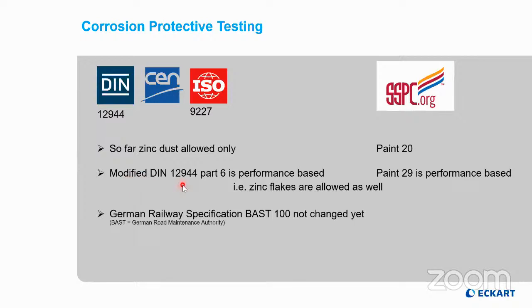This norm has now been changed into also a performance-based norm, meaning zinc is still specified in the norm, but not by 85% loading. It needs to be loaded into the formulation and provide a good corrosion protective performance similar to that of zinc dust. The same applies for the American SSPC Paint 20 norm. So far, again, it specified a minimum zinc dust content of 85%. Now Paint 29 is issued, which also allows working with a lower zinc content as long as performance is the same as with zinc dust.